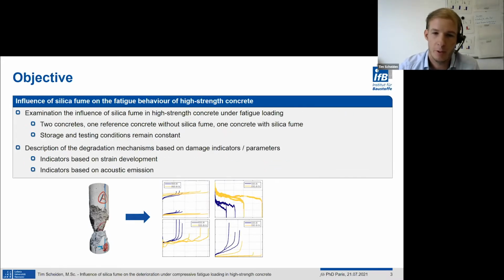Therefore, the main objective of this research is to examine the influence of silica fume in high-strength concrete under fatigue loading. Two concretes were investigated: one reference concrete without silica fume and one concrete composition with silica fume. The storage and the testing conditions remain constant. With these concretes, the degradation mechanism based on damage indicators and damage parameters will be described. The considered damage indicators are based on the strain development and on the acoustic emission.